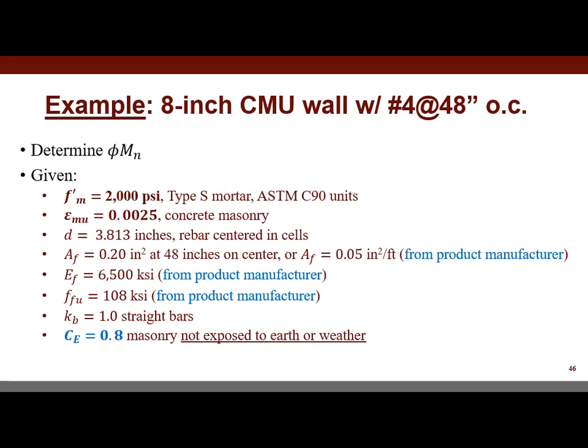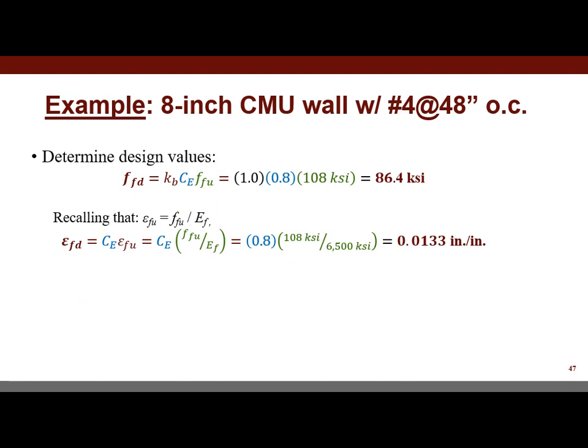But here's an example of an 8-inch CMU wall. It's got the masonry characteristics, the maximum usable strain in masonry, and location of the reinforcement, the amount of the reinforcement. These values for A_f, E_f, and the tensile capacity all come from the manufacturer, or those ASTM minimums. And if this is not exposed to earth, we're going to use a 0.8. There's no bend, it's 1.0. So first step is we calculate our design value here. Again, we saw that equation earlier, 86.4 ksi. We can relate stress and strain. It's linear elastic, Hooke's law, you guys remember that. And we can calculate the strain value from Hooke's law.